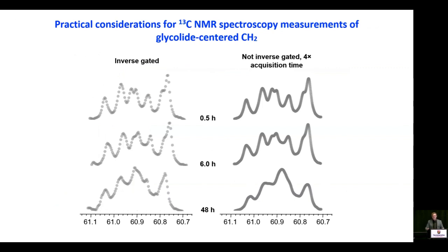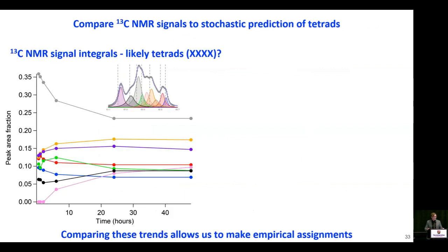Some experimental notes, right? You don't necessarily need to do an inverse gated experiment, but you need a long acquisition time, and a high density of data points within that region is going to help you do this fit. So if we just look at these peaks as they change, we don't know what they are yet. You'll see that they change as a function of reaction time. Okay, there are some peaks that start high and go low, some that kind of stay in the middle, and there are some peaks that start at the bottom and increase. Based on the number of peaks, we thought that these are likely compositional tetrads, so sequences of 4.